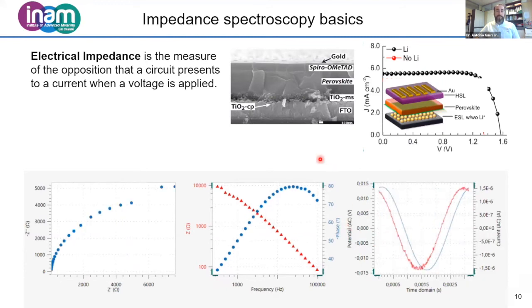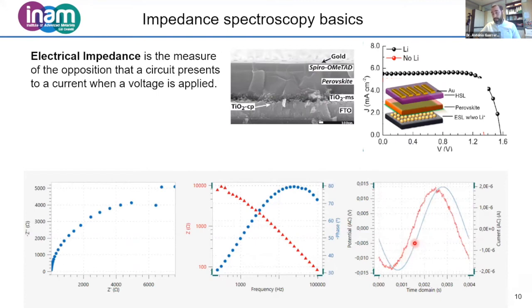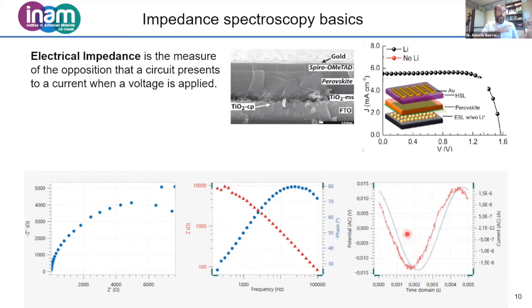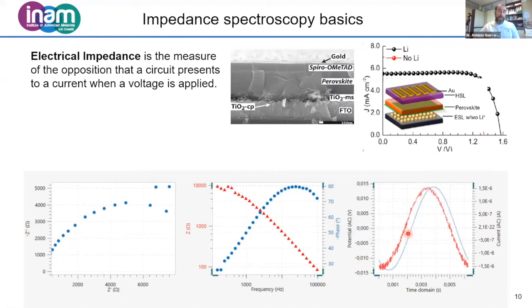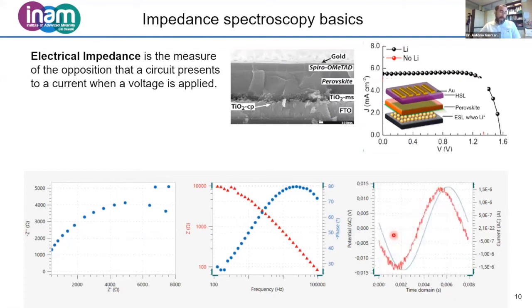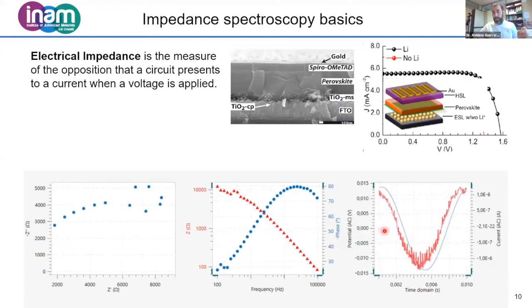For impedance spectroscopy of perovskite solar cells, it's quite common to observe noise as we start to move to low frequencies. Also, I need to mention that frequency and time are connected. One is the inverse of the other. So low frequencies means long measuring times. The impedance spectroscopy measurement can be relatively fast, on the order of a few minutes, if you stop at high frequencies of hertz or kilohertz, and it can be very slow if you go to frequencies of millihertz.